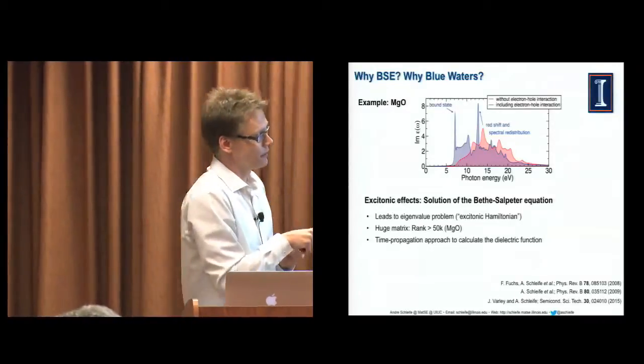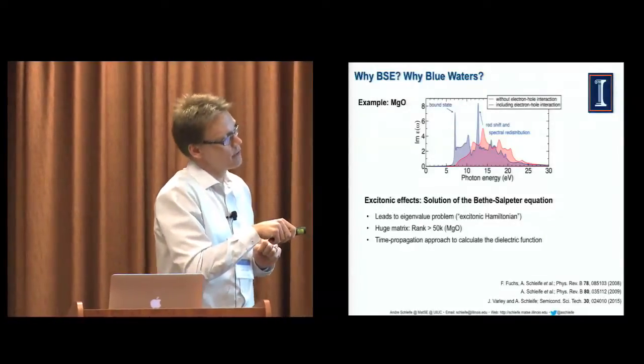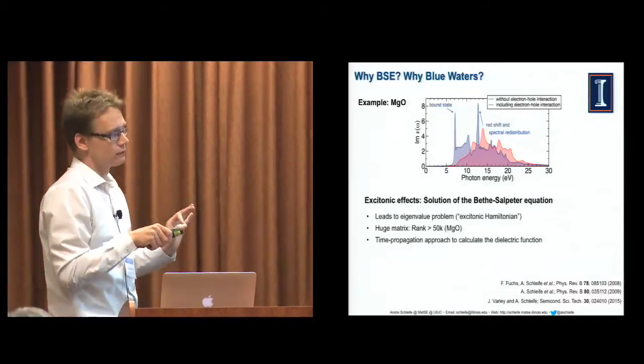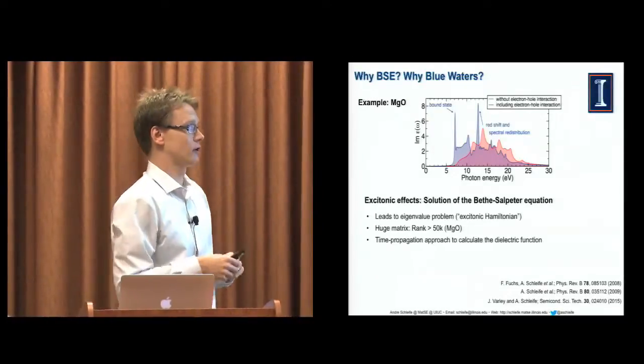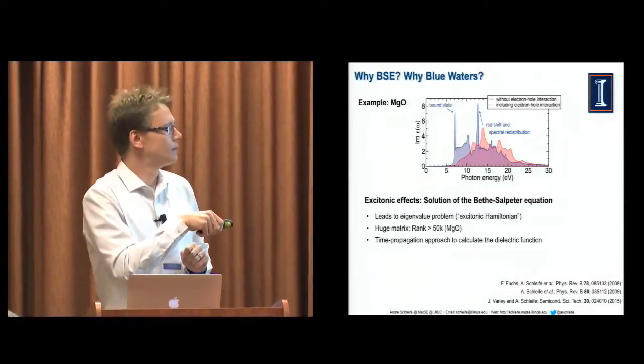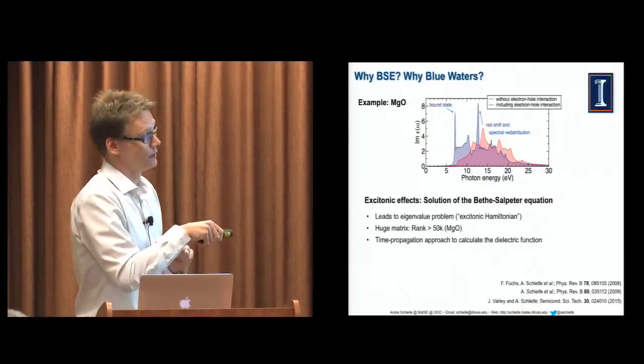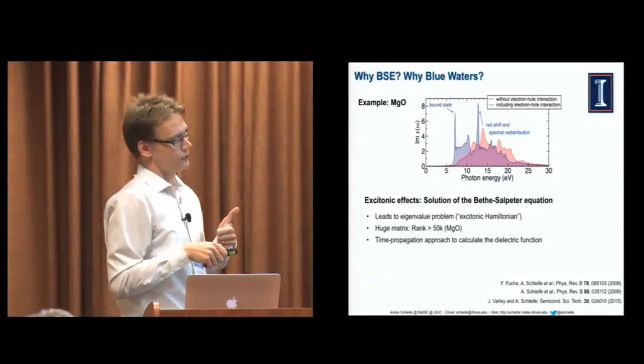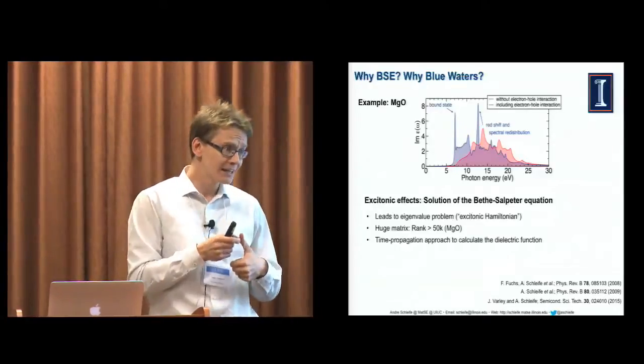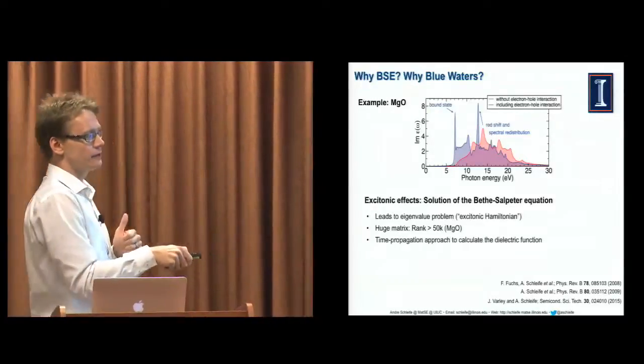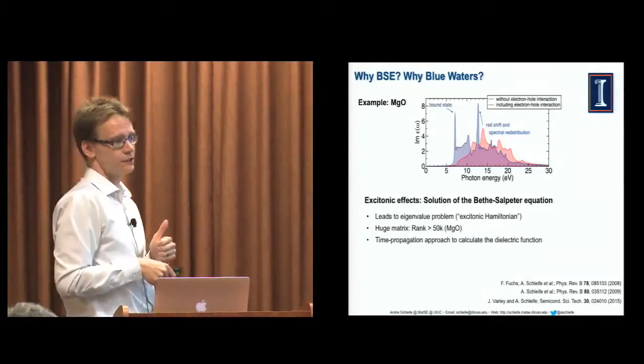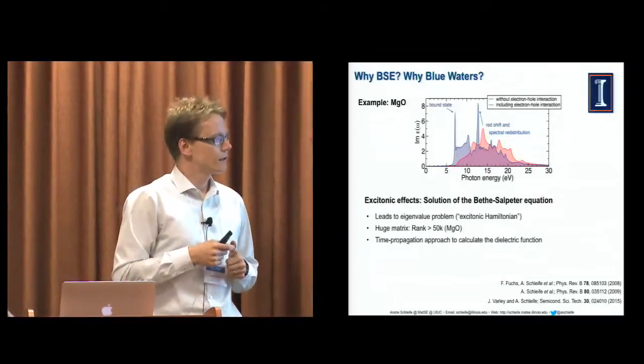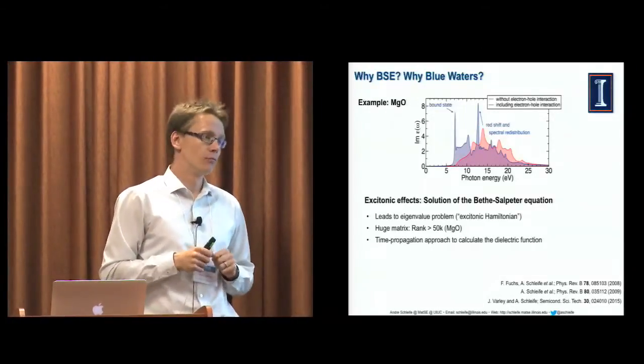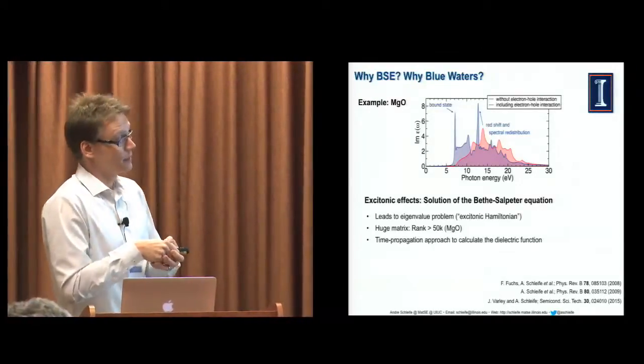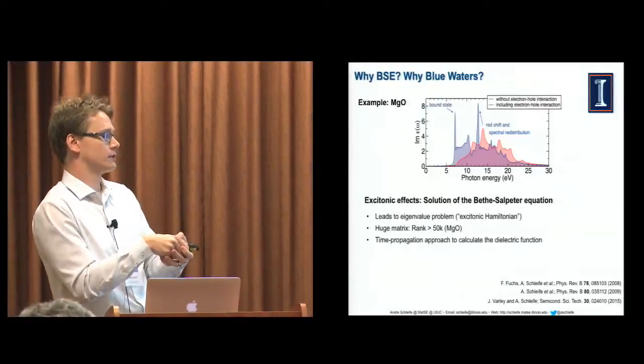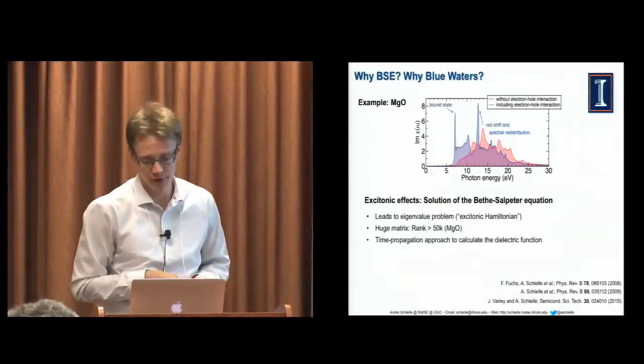The rank of this matrix can be on the order of 50,000 for magnesium oxide. For indium oxide, it's going to be much larger. I'll show you that in a minute. So we have a large matrix that we now have to deal with. And there are two ways that you can deal with it. You can either diagonalize it directly. That may be doable for a matrix with a rank of 50,000, but it's already getting painful. But if the rank is something like 300,000, then it's more or less impossible. So that makes it computationally expensive. And we actually use a so-called time propagation approach to circumvent that.